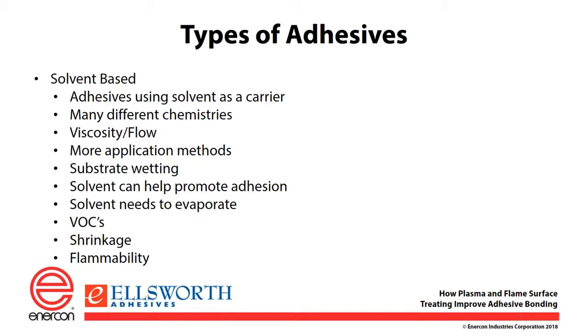They typically will have lower viscosity and they flow well, which opens up your application methods. You might find these spray applied, for instance, where a 100% solids material might be more difficult to spray. The solvent has an advantage in that it can help promote adhesion to plastics. That's because the solvents that are present can actually bite into the surface of the plastic and promote the adhesion. However, when you're curing these systems, the solvent does need to evaporate, so you may want to use ovens to expedite the evaporation process.